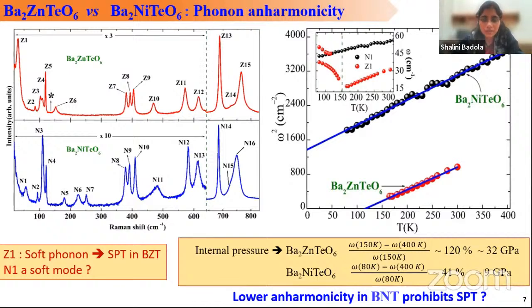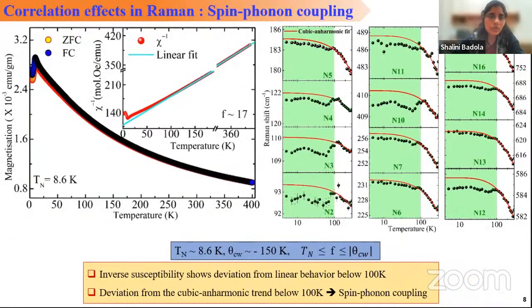But let us recall that there is a strong magnetic frustration in case of the nickel system. And a strong magnetic frustration should promote a structural transition or lattice distortion in the lattice. So therefore, to understand the same, we further carried out the Raman measurement down in the magnetically ordered phase, where we found that most of the phonon modes deviate from the general cubic anharmonic behavior below 100 Kelvin. When we measured the magnetic data, we found that the inverse susceptibility also shows a deviation from the linear trend right around the same temperature. This gave us an indication that there is a coupling between spin and phonon degrees of freedom. Also, the spin-phonon coupling is sort of relieving the magnetic frustration in the system, which is also helping in prohibiting the structural phase transition in BNT.